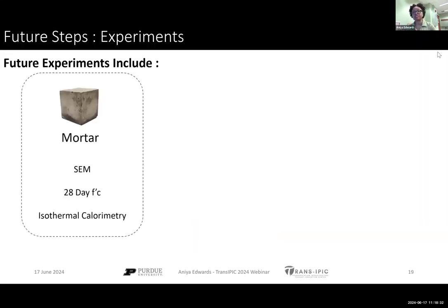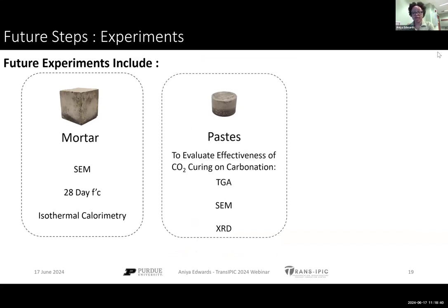So future experiments include some mortar analysis for SEM, 28-day compressive strength, and isothermal calorimetry, as mentioned earlier. For our paste, we want to evaluate the effectiveness of CO2 curing on the carbonation of our samples. So we're going to be using TGA, that's thermogravimetric analysis, SEM, scanning electron microscopy, and XRD, or X-ray diffraction, to see what really is going on in our samples.